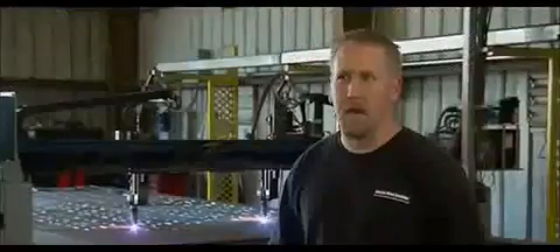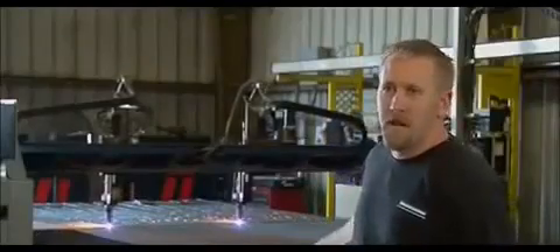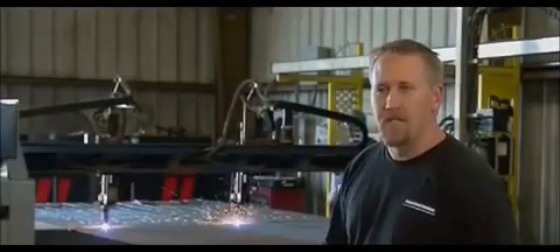As it comes out of the nozzle, it cuts at about 25,000 to 30,000 degrees. The plasma is also flowing at up to 22,000 feet per second. That's fast enough to zip from New York to Los Angeles in a little over 10 minutes. So what you're seeing there with the sparks that come out is essentially because the material has nowhere else to go. So until it starts cutting, it basically shoots the sparks back out of the top. But once the plasma fully penetrates, the computer-controlled cutters have no trouble crafting any shapes fancied by its operators.